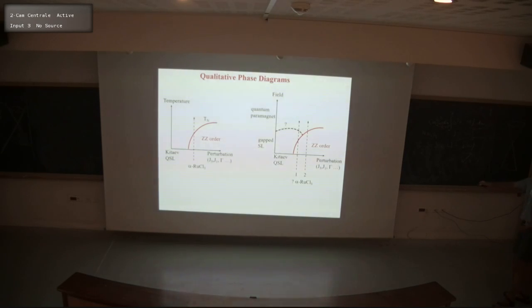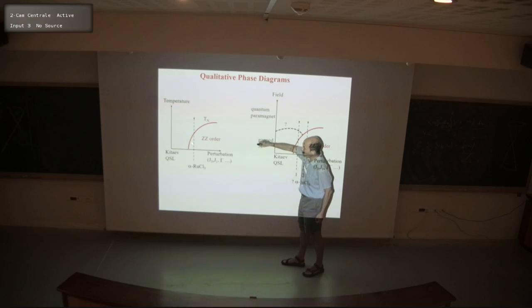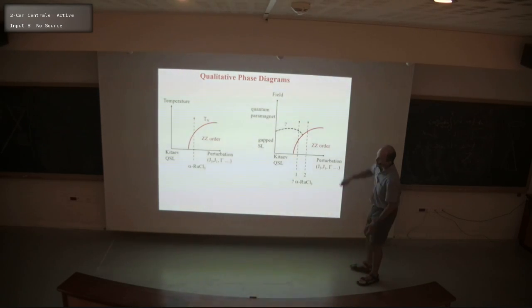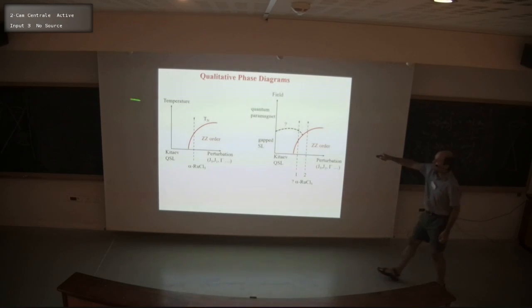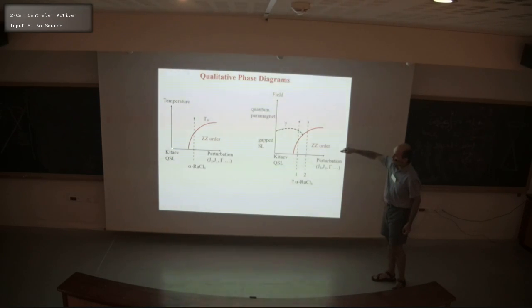But there are other terms, J3, J1, gamma, which are present and stabilize the zigzag order. And as Lucille explained in her lectures, the Kitaev spin liquid is stable to perturbations. So we need some finite perturbation to take the system away from the quantum spin liquid. Then one would expect generically that there is some phase transition boundary, the solid line indicates Tn, that would go to higher temperatures as the perturbation increases. The material is believed to be located somewhere close to this point, and so in temperature one would enter the zigzag order ultimately. The question is whether at these finite temperatures or higher energies in the inelastic spectrum, one can still observe some of the physics that's characteristic of this point up here.